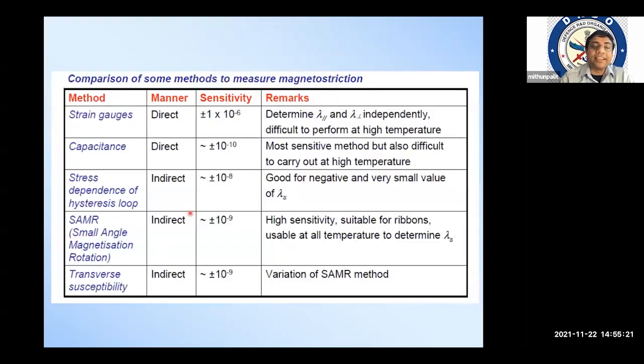Magnetostriction is measured using various methods. The most widely used method is the strain gauge method, where the gauge is connected to a Wheatstone bridge, and the bridge unbalanced potential due to the change in the length of the magnetostrictive alloy is measured. Apart from that, there are the capacitance method, the stress dependence hysteresis loop, the SAMR method, and the transverse susceptibility method.